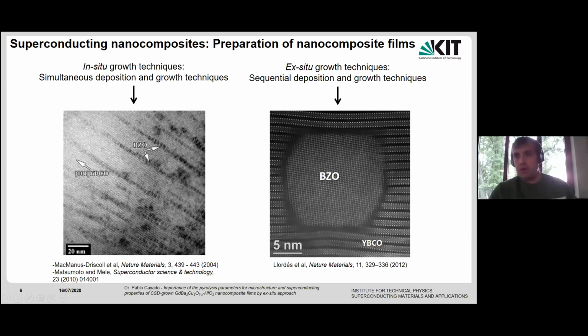in order to prepare these nanocomposites, usually we can distinguish between two different techniques, or two different ways. The first one is associated to the in situ growth techniques. We call them in situ growth techniques because we have a simultaneous deposition and growth process. So it's, for example, the PLD or the sputtering, where while you are depositing, the phase is already created. In this kind of techniques, usually we obtain self-aligned or self-organized defects, for example these typical nanocolumns.